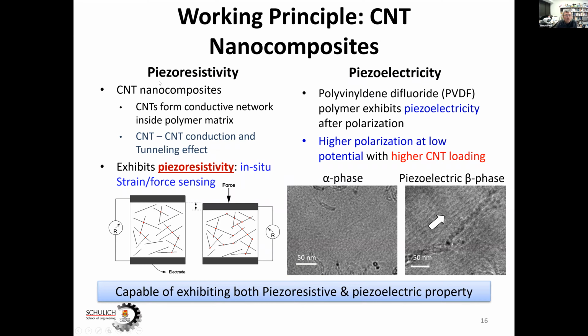So how does it work? This is a piezoresistive. We put carbon nanotubes onto a polymer. Carbon nanotubes are very conductive, so their electrons can travel when these carbon nanotubes touch each other. Another way of traveling is what's known as the tunneling effect. If these carbon nanotubes are close to each other, let's say about an angstrom, electrons can hop. That's known as the tunneling effect. If you apply a compressive force, the distance between these fibers gets closer, and you have a lot more conductive paths. So when you apply force, your resistance goes down. When you apply tension, resistance goes up. That's known as a piezoresistor.